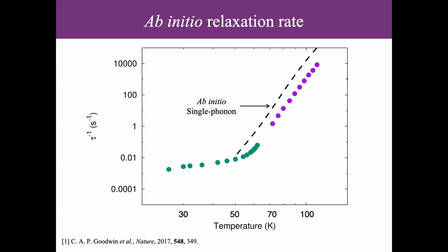So you need only those phonons that modulate your spin Hamiltonian. But that's not true, right? Because we know at high temperatures, it's the higher energy ones, the intramolecular vibrations. Because this was a gas phase calculation, for instance, we only have intramolecular high energy vibrations, and from this we're getting pretty close to the Orbach regime. So I disagree with that, because you assume that at low temperature, your molecular vibrations are inactive.